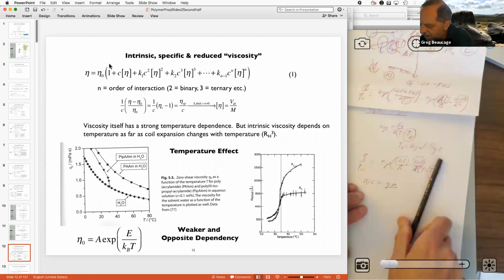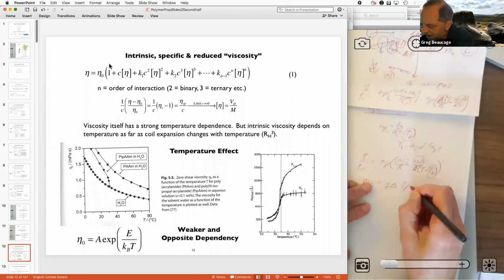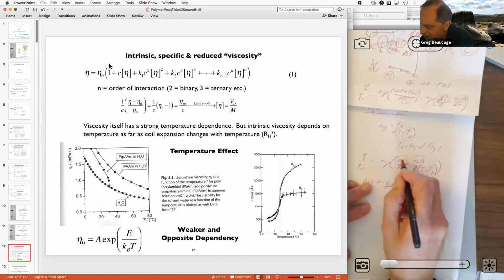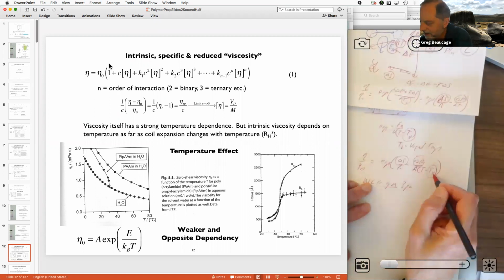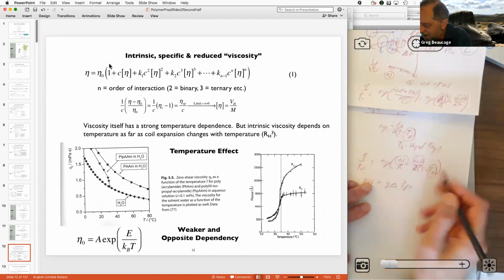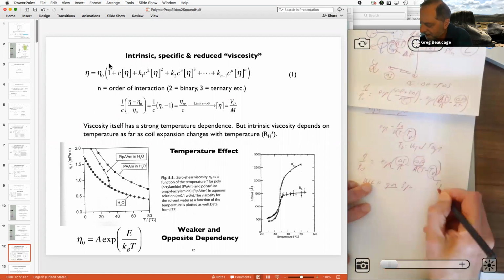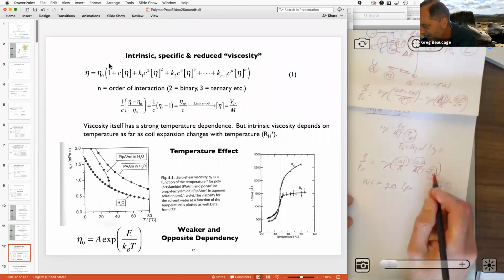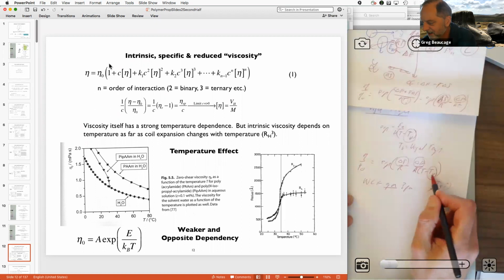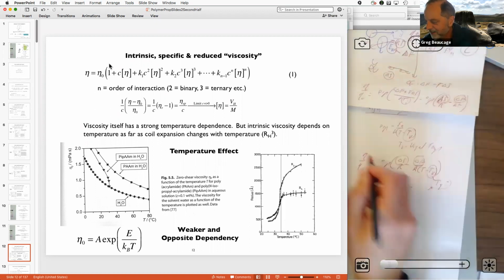It also has three parameters. And you can explain those three parameters in terms of entropy, enthalpy and this Vogel temperature, which somehow should be glass transition. It isn't usually exactly the glass transition, but it's near it. Since a glass transition is a kinetic phenomenon, it changes with the rate. So this Vogel temperature doesn't change with rate, even though it's dependent on viscosity, which is dependent on rate.